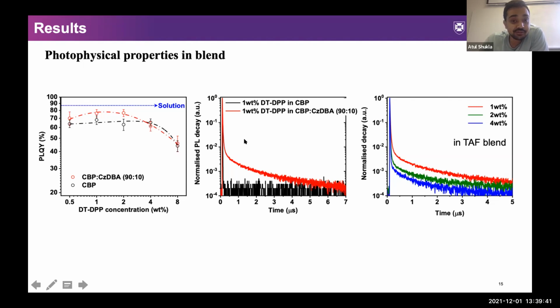And the evidence of triplet upconversion can be seen in the system through this delayed fluorescence. And the evidence of increased Dexter transfer from CZDBA to DPP can be seen here in this TCSPC data. So we can see the reduction in delayed fluorescence, which corresponds with the quenching of triplets of CZDBA itself.